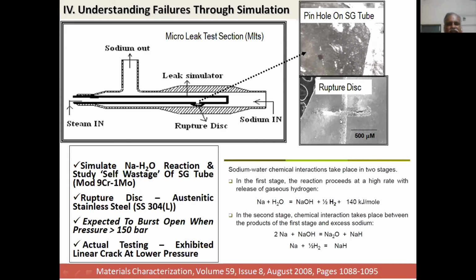And they expected that when the steam is passed inside and pressurized, this will open out as a petal and interact with the sodium which is flowing in the outer tube here. And unfortunately, this rupture disc failed not like a petal but as a linear crack. So they wondered why it had cracked along a line. They wanted to know the reason, and we examined it in detail. In the next few slides, I will tell you what the reason was why a linear crack emerged.